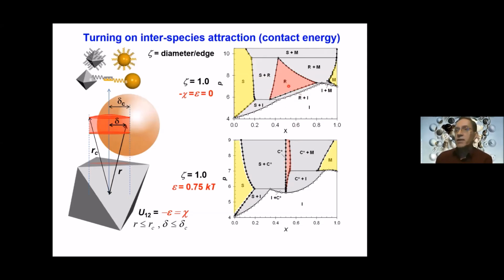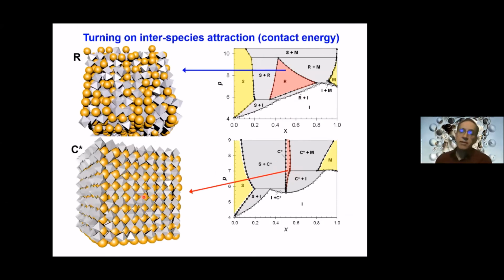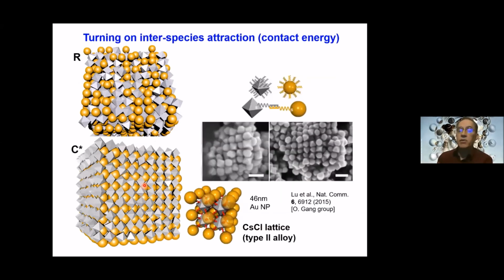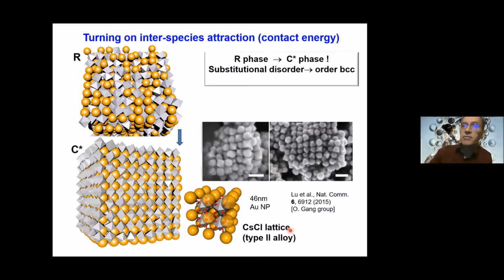In particular, the phase that appears in the middle is no longer this phase R, but another phase that I'm calling C star. And if I show you a snapshot of that, you can see that this is a compound phase. And indeed, it corresponds to the cesium chloride lattice that we were expecting, also because that system had been studied before by using DNA graphs to create this energetic selectivity. So it was comforting, I guess, that we were able to go from basically a substitutionally disordered phase to one that contains substitutional order. Now, interestingly, both are BCC lattices, just that this is substitutionally disordered, this is ordered.